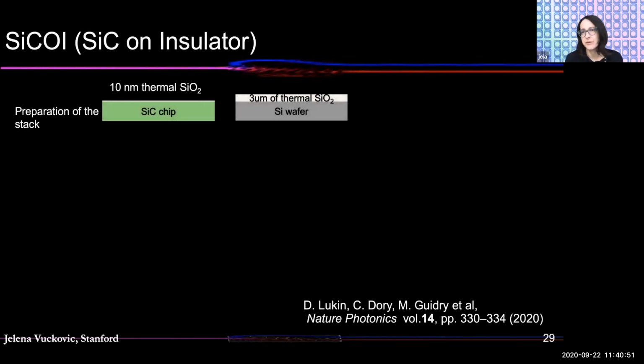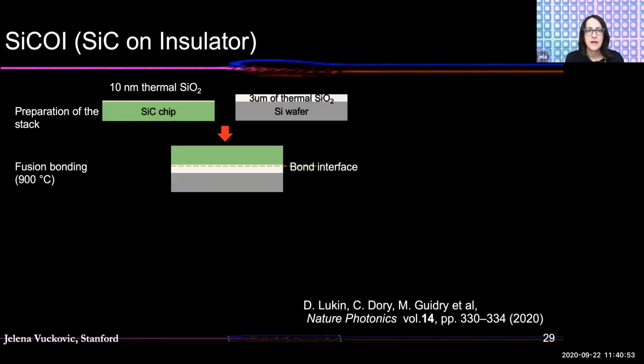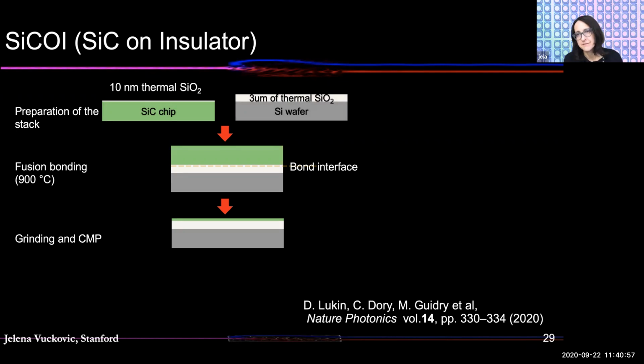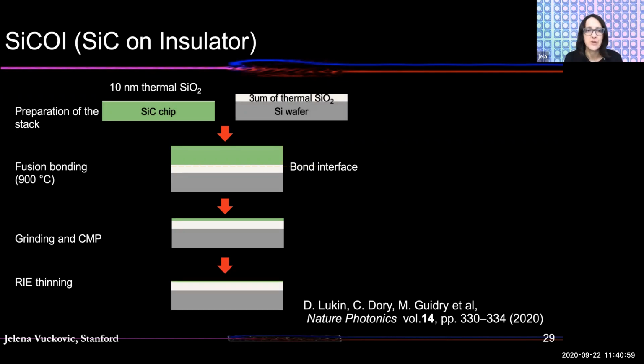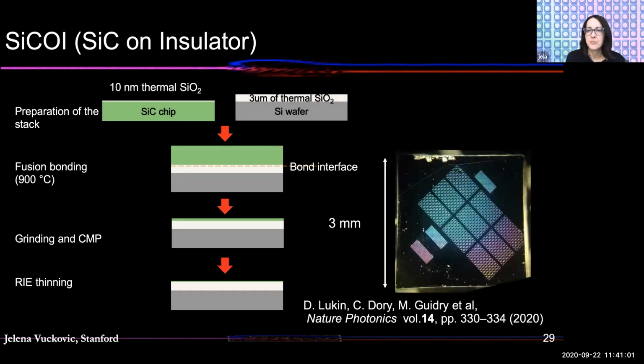We do a very simple thing. We start from silicon carbide, bond it on oxidized silicon, and then thin it. First do coarse thinning, then fine thinning, and then end up with chips of silicon carbide on insulator. And this process is actually also scalable to larger chips, but for us, a few millimeters of a chip size is sufficient to do a lot of experiments and build pretty much all of the circuits that we're interested in.